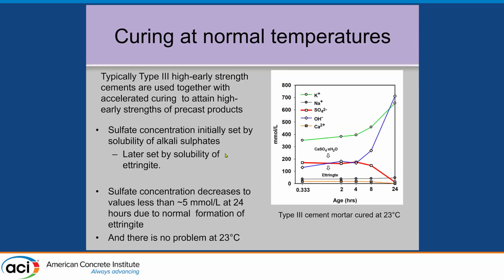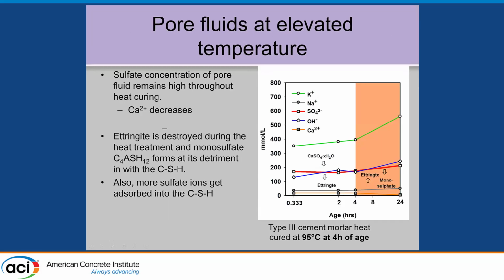Now, when you cure concrete at normal temperatures, this is a type 3 cement, the pore solution analysis over the first 24 hours on a log scale. Typically, you'd see the alkalis in solution, and you'd see hydroxyl in solution, and the sulfate in red here would typically form gypsum and ettringite, precipitate gypsum and ettringite, and then the concentration would come down, then the hydroxyl concentration would go up to keep a balance of cations and anions. So that's what normally goes on. Usually by 24 hours, there's no significant sulfate left in solution. At room temperature, that's what happens. So there's no problem there.